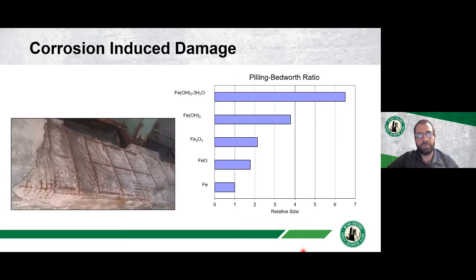So with corrosion of reinforced concrete, what is really causing the damage? The damage is really the result of iron becoming iron oxide. Iron starts to grow in size. It's an expansive product. As iron becomes rust, iron oxide, it grows up to 6.5 to 7 times its original size. And if we have an expansive product inside concrete, that expansive product will crack and delaminate concrete and cause spalling. That's really what's causing the damage of the concrete due to the steel corrosion.